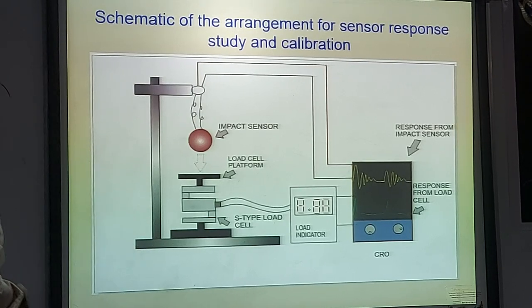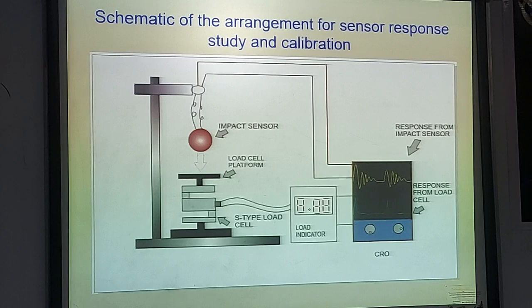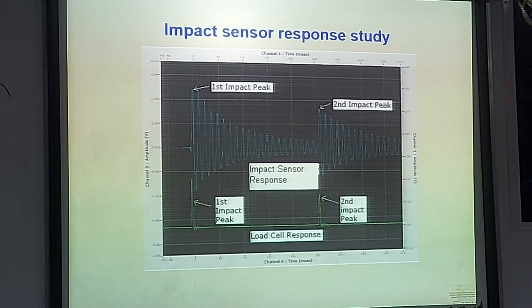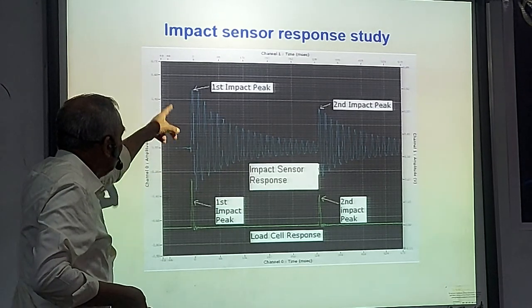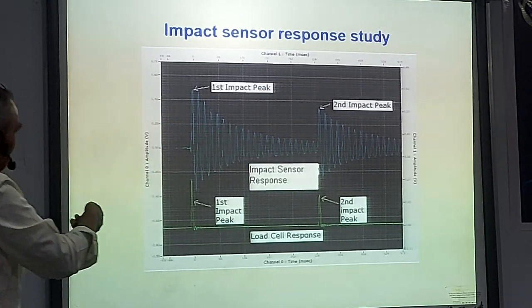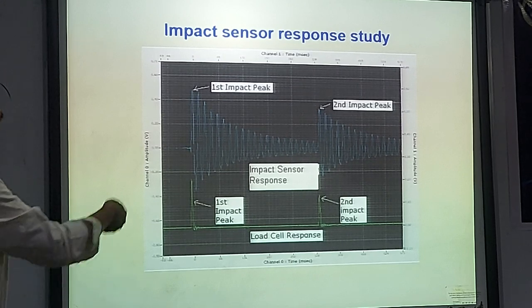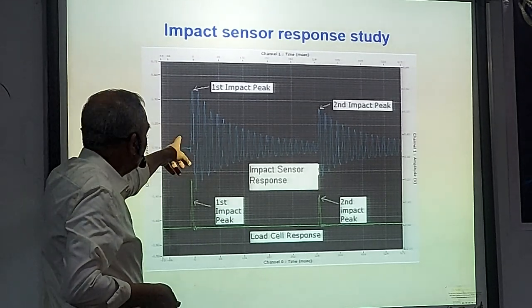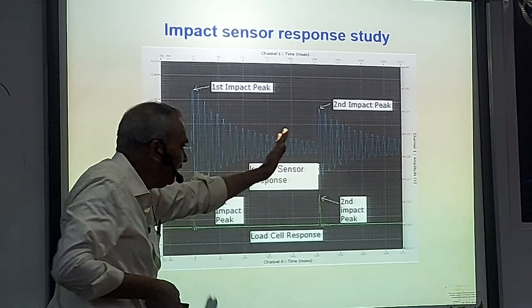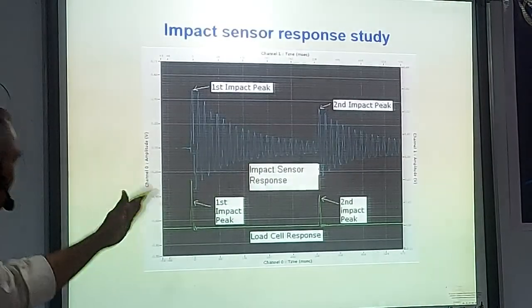So in order to study this response, we have used a load cell. What we have done is this impact sensor was dropped from different heights to make an impact with the load cell plate, and the response was recorded. It's a simple arrangement made in the laboratory, and some of the responses that we got are shown here. See, when the impact sensor makes the first impact, this is the maximum amplitude that we get. The signal decays and it rebounds, making a second impact. Compared to the magnitude of the first impact signal, this is lower, and it comes down with subsequent impacts, third, fourth, etc.